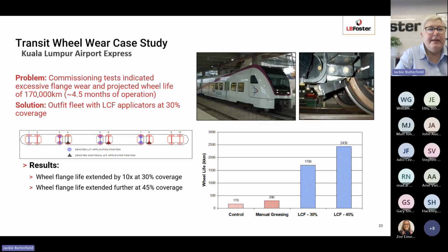And then the final case study is an onboard solid stick case study. This was Kuala Lumpur Airport Express. During the commissioning of this network, excessive flange wear was experienced, and they projected that the wheel life for the vehicle was only going to be 170,000 kilometres, which was effectively 4.5 months. So from new wheels to scrap was 4.5 months. So obviously not acceptable. So the solution was to fit the fleet with flange sticks, L.B. Foster LCF sticks, at coverage of 30% of the axles.